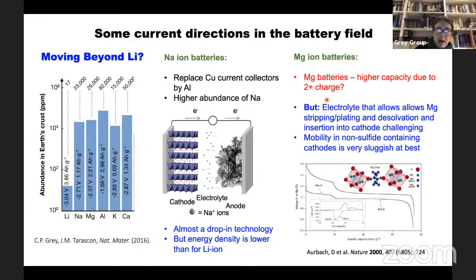And I'll come back to that later. So let's think more outside the box. What about the rest of the periodic table? So the next one along, obviously, is magnesium in terms of size. And, you know, for the chemists amongst you, in many ways, magnesium behaves quite similarly to lithium, except, of course, it's got a 2+ charge. And the advantage of a 2+ charge is that you can find a material that needs less space to hold the magnesiums. And so you could imagine this is a layered compound with lithiums, but if you had magnesiums in there to compensate charge of the transition metals, you'd only need 50% of them, which means if you had the same number of magnesium, then in principle, you could pull more electrons out of the compound.